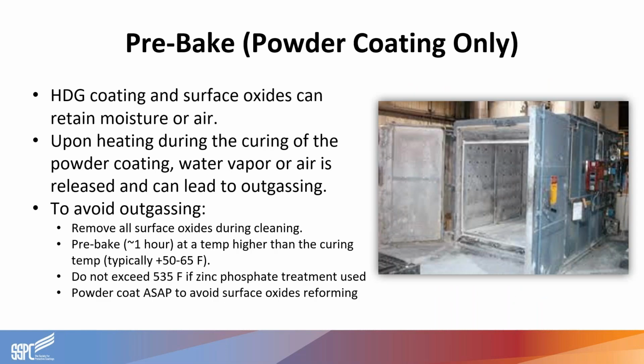With pre-baking, that is the next step specific to only powder coating. So once surface roughening has been performed, you're ready to apply the coating, but you need this intermediate step between surface prep and application of powder coating. And this is to prevent pinholes or blisters in the powder coating that can occur if you have any trapped water vapor or air within the natural roughness of the zinc coating that can expand and then leave the surface during curing of the powder coating, leaving you with those small craters or blisters.